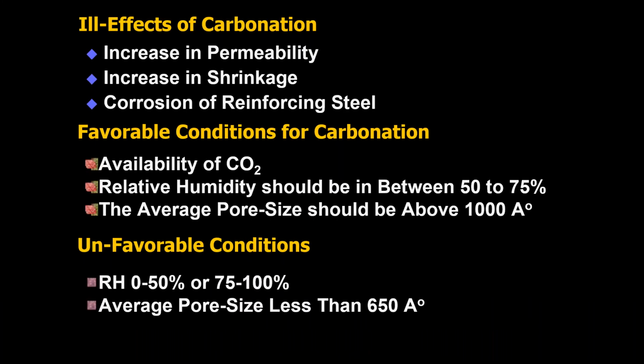And before talking about the carbonation, I would like to explain why we should worry about the carbonation. It increases the permeability and shrinkage, and also it will affect the corrosion. What are the favorable conditions for carbonation to take place? Availability of CO2, relative humidity between 50 and 75%, and also average pore size has to be more than 1000 angstrom units.